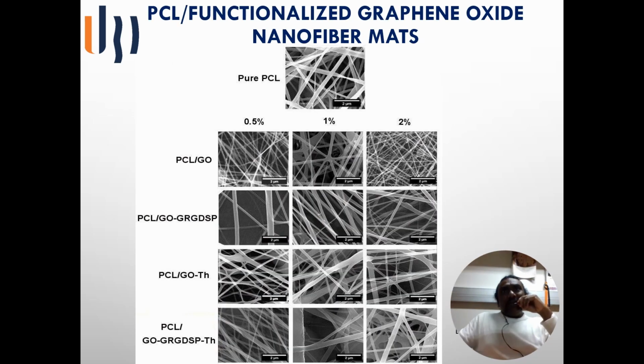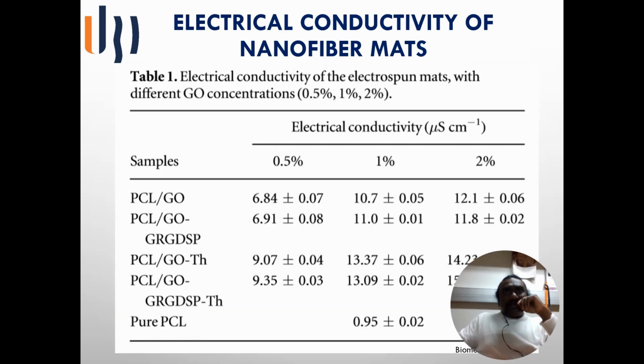And these solutions were electrospun in order to get nanofiber mats with graphene oxide and different functional group functionalized graphene oxide at different loadings like 0.5%, 1%, and 2%. And here you can see some electrical conductivity characterization of these nanofiber mats. These are microsiemens level, but this electrical conductivity is sufficient for biological cells to communicate and grow on these mats.